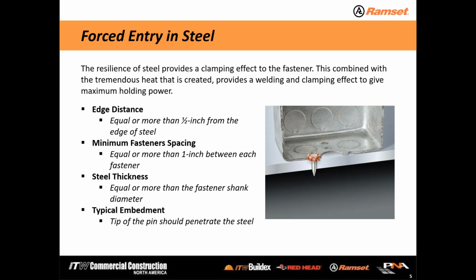So steel thickness is pretty important as well, especially with using smooth shank fasteners and powder actuated and gas fasteners. So the general rule of thumb is the steel thickness should be equal to or greater than the fastener shank. So what would tend to happen if it were thinner is that while the fastener would go in, I might put other fasteners in that same member. The first few fasteners might come loose.